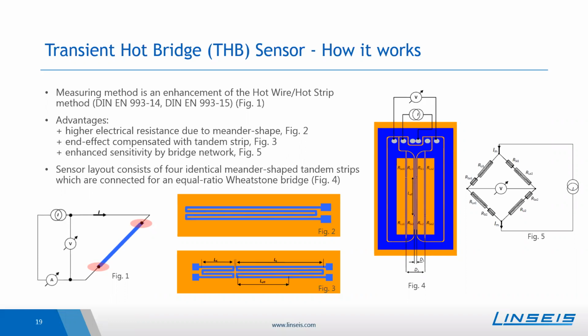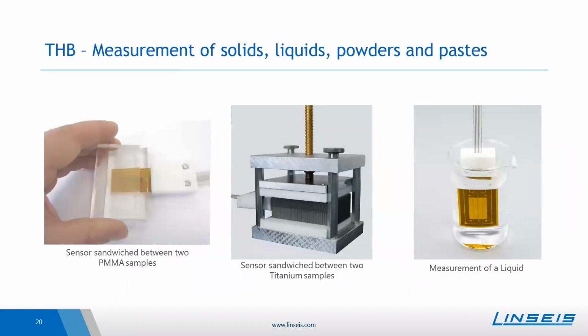So there are coming up some further questions. So if any pressure is needed in the sensor sample sandwich, let me go to the slide with the photo. Here you see that we typically need to press the configuration together. One does not need a too strong pressure, but just some light pressure so that one can enhance the thermal contact between the sample and the sensor. So typically, a pressure of 0.5 kilogram is enough.